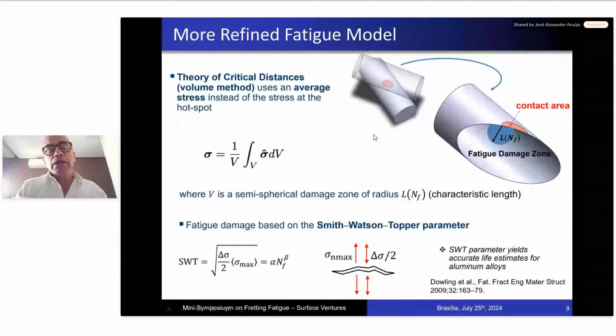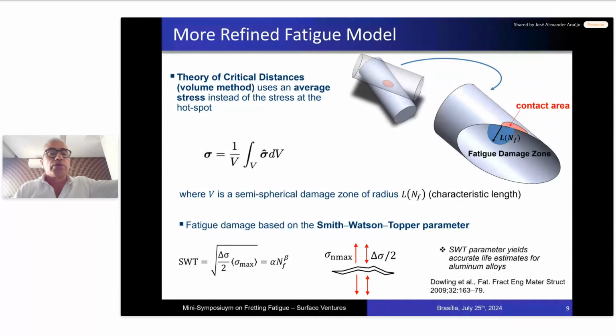So here we are going to present a more refined strategy to try to approach this problem. We are going to use a critical plane criterion, the Smith-Watson-Topper parameter. We could try another. In this case, we have seen that the Smith-Watson-Topper parameter works quite well to estimate life of these aluminum wires.